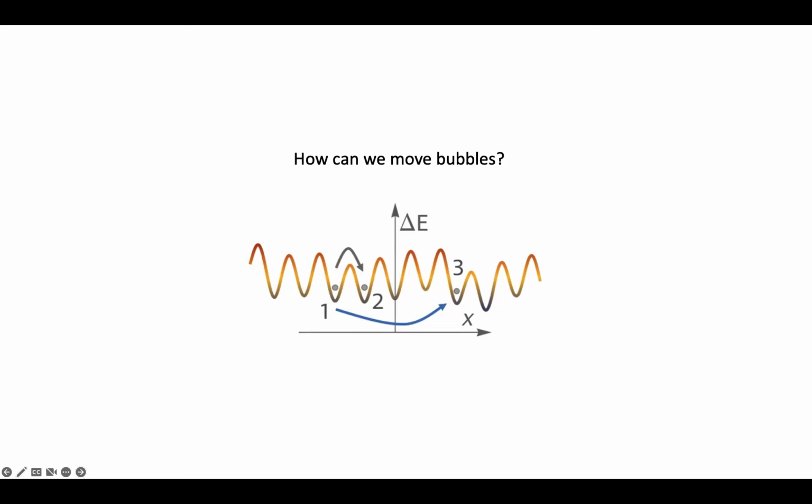And those barriers are like the motion of a domain wall. It's essentially associated with the energy that is needed to switch the dipole, but not one dipole in this case. So you have a small up domain, and to move it a little bit, you have to switch those dipoles that are surrounding the bubble, and that's what produces the barrier.